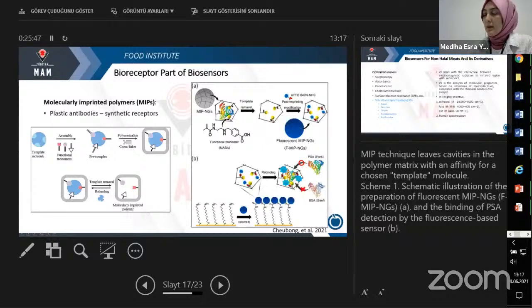And here is a study where they developed MIPs against porcine serum albumin. They did the same procedure, and after the template removal, they had a post-imprinting modification by the addition of a fluorescent molecule, and they immobilized the MIP on gold nanoparticle, and at the end, they put the MIP with the gold nanoparticle on the surface of the electrochemical biosensing electrode. And they see that when the porcine serum albumin is bound to the MIP, it gives the fluorescent signal, but bovine serum albumin cannot be bound to this MIP and doesn't give any signal. So it's a very nice study.